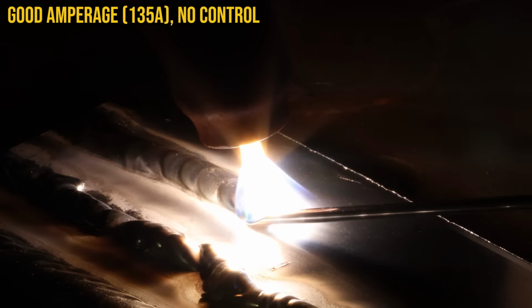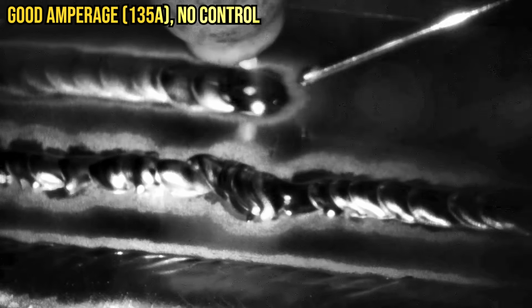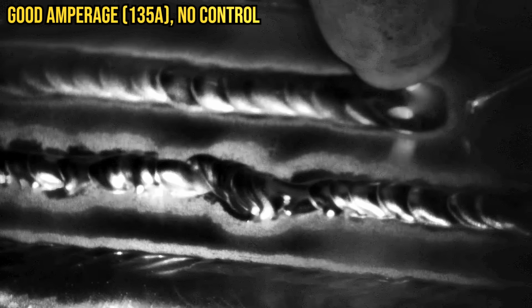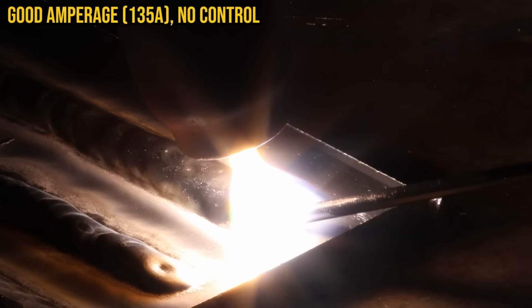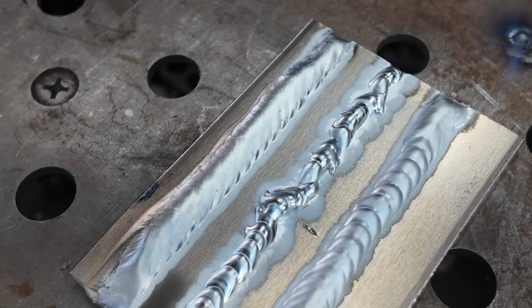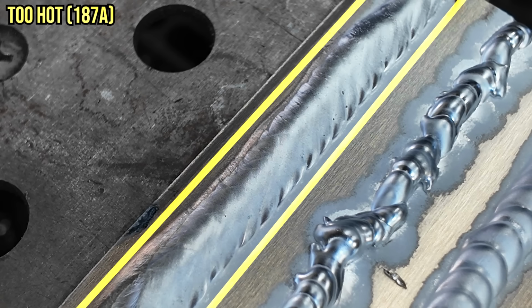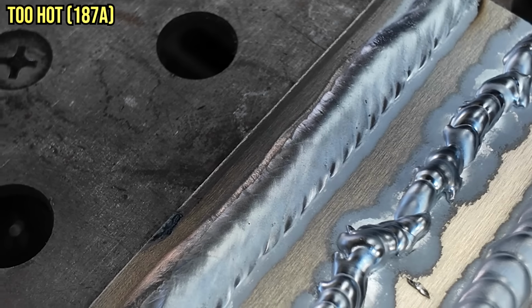And then if you don't have any way to control that amperage, even still, starting off at the beginning, in the middle, it seems to be okay. Then we get to the end and we're going to blow it out, even if we're in the middle of those amperage ranges at like 135. And we can take a look at these welds right here. We can see the first one clear as day is super duper hot. We got no definition in those ripples. It's washed out, and towards the end, we're just blowing it out.